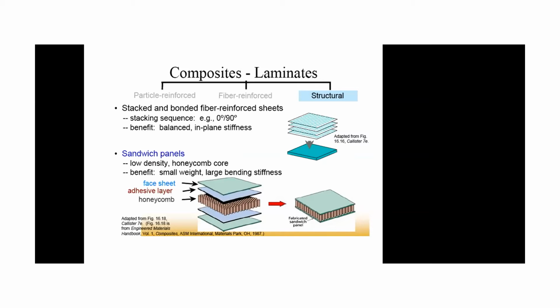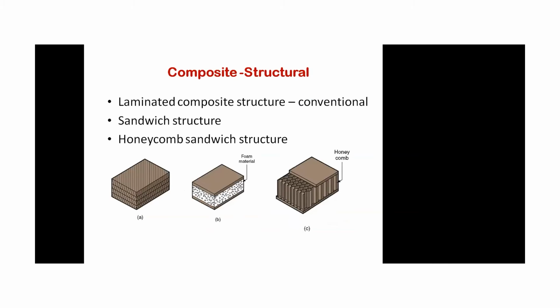So here in this case, of course, the size, the area of the reinforcement as well as the matrix is more or less same size, but the thickness of the different layer can be different. So you can fabricate sandwich panel, and in our lab we are making this kind of material using foam. Okay, we are putting foam in between, and we are putting polymer or aluminum material around this foam material, and we are making sandwich panel. Sandwich panel can be of either first laminate structure, sandwich structure, or honeycomb. Both are possible.